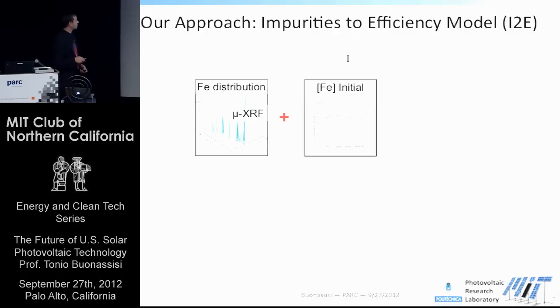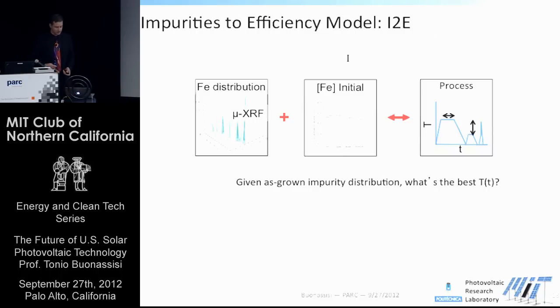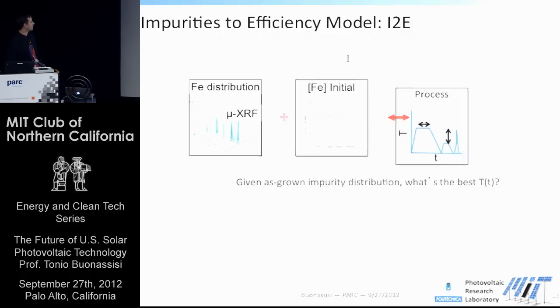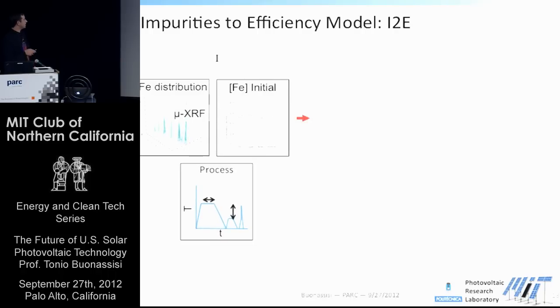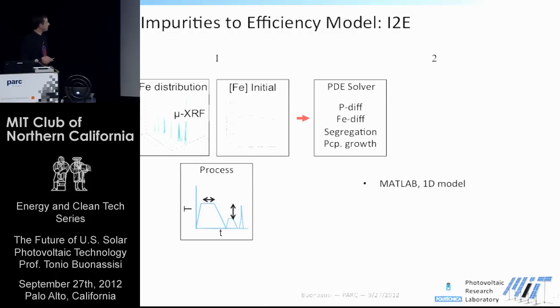We also can measure the total concentration of the defects inside of the material using bulk analyses. And we input the time temperature profile, the temperature recipe, if you will, for processing the solar cell. And this we call the impurities component of our simulation or our model. We use a partial differential equation solver to describe the diffusion of phosphorus into the wafer, forming the junction that